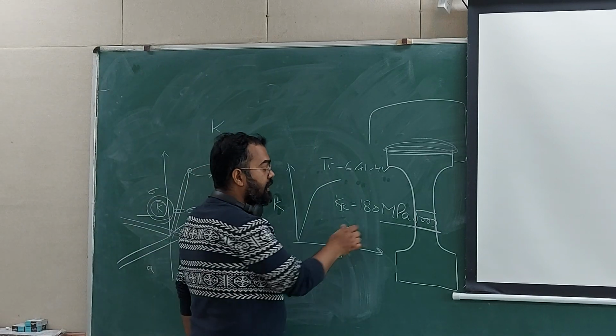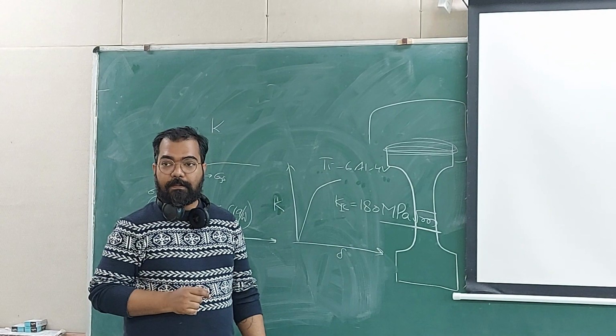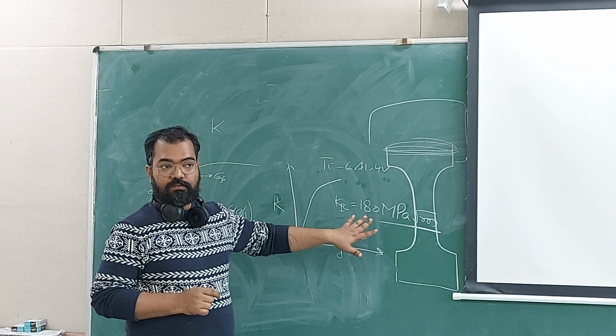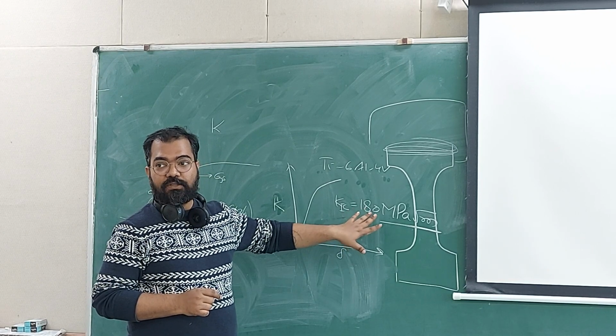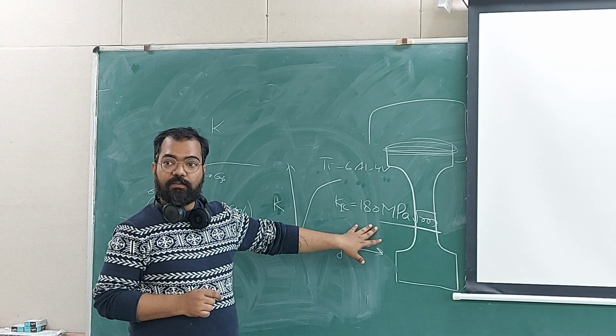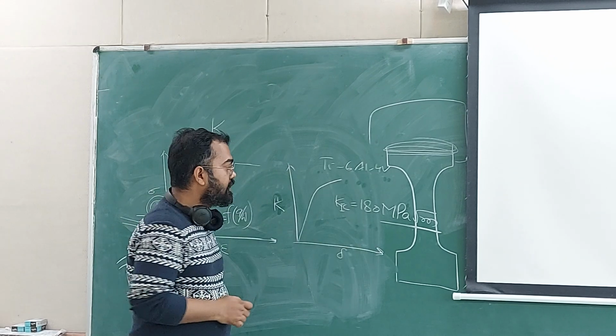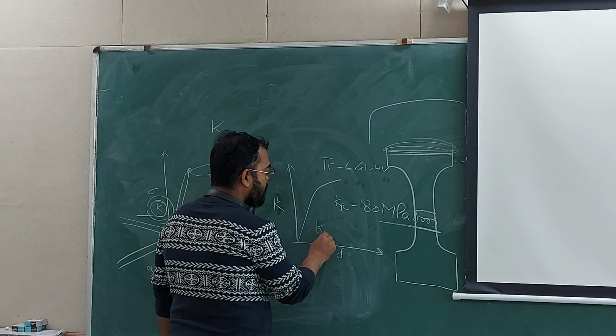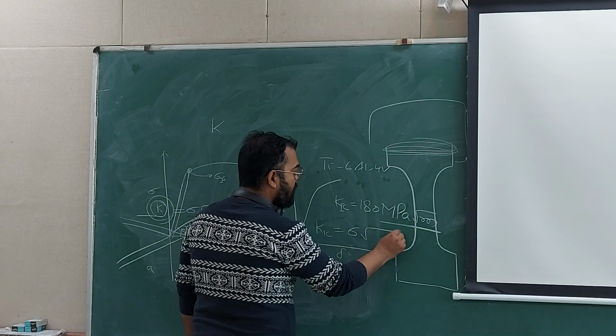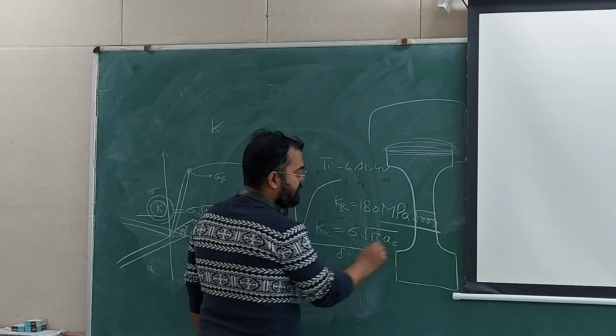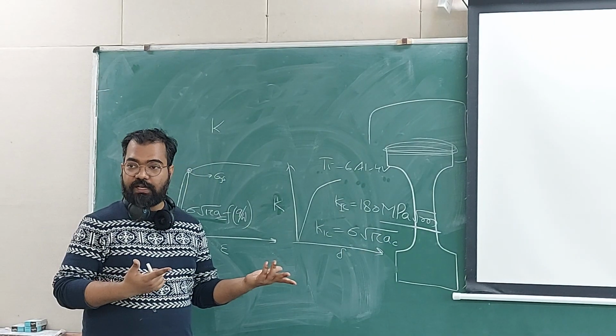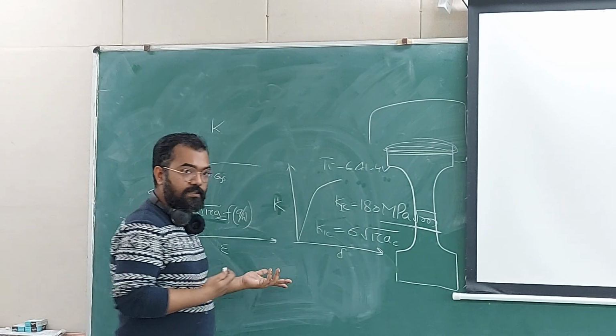If this is the value of K1c, I can find out how large a crack I can accommodate in my component. From this I know that this must be equal to sigma root over pi a_c. That's the value of the critical crack I can have in my system.